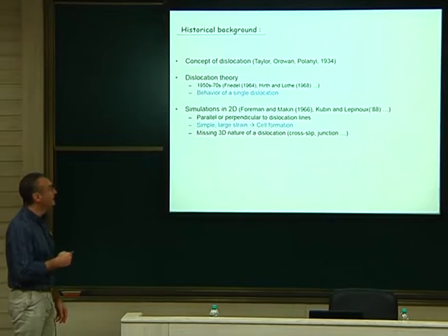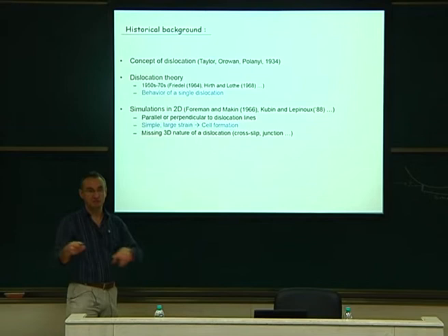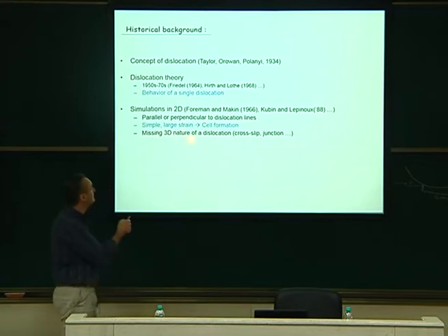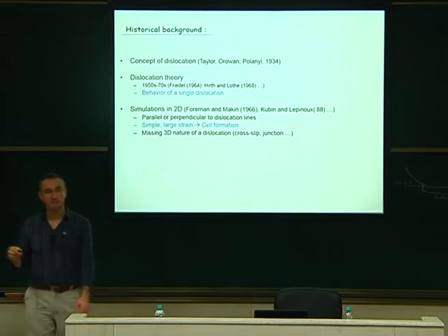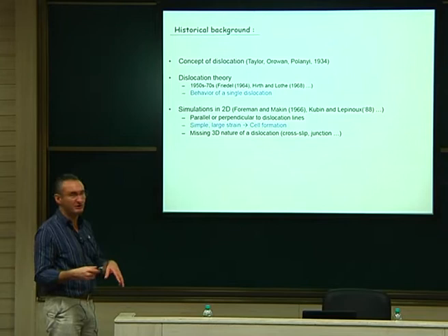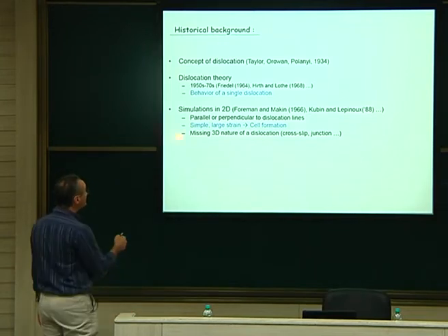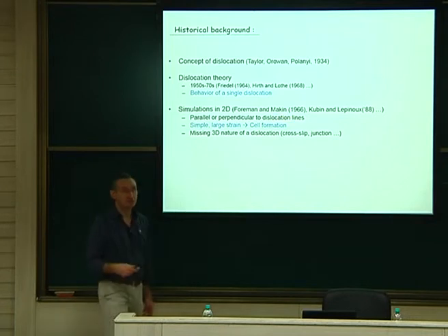So, very simple. Since it is simple, you can reach large deformation compared to the 3D simulation. It's very nice for that. And then you can have access to the cell formation, how dislocations merge and form cells, that we have very much difficulty to do with 3D simulations. But things are missing. It's 2D, it's not 3D, and this is a big problem.